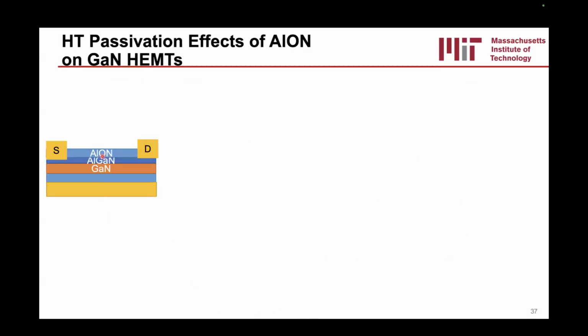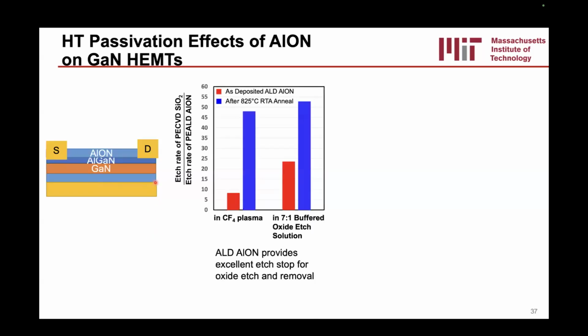We developed this ALD aluminum oxynitride layer. The nice thing about this layer is that it has really good selectivity to SiO2. So in the red, if you don't anneal it, it has a selectivity of about 7 in fluorine plasma, and it has a selectivity of about 20 in HF or BOE. And then if you anneal it at, for instance, 825 Celsius for like a minute, you can actually increase the selectivity to about 50, which is really good for an etch stop layer, and that's what we needed.